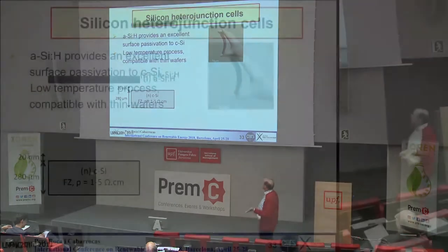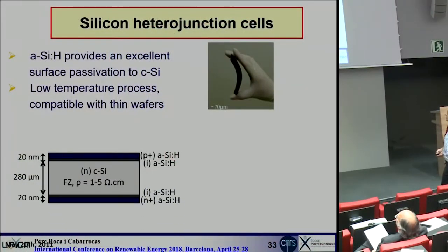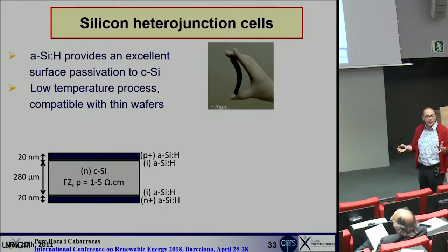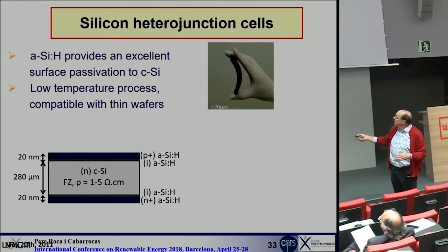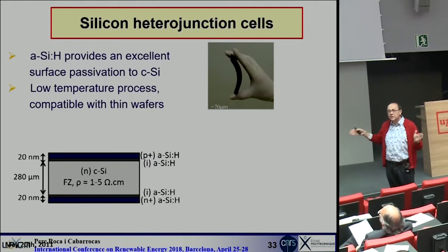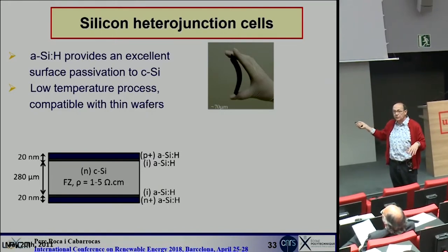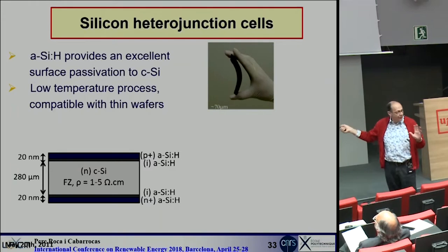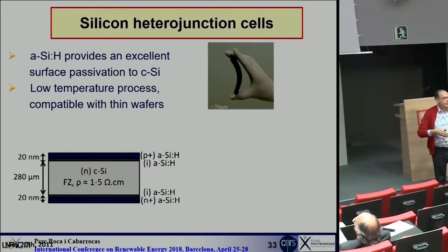Heterojunction solar cells: we are going to change the substrate, instead of having glass or foil, we are going to work on crystalline silicon. That's the battle horse. So let's take crystalline silicon, and then the same, you put it in the reactor, you deposit the intrinsic, p-type, intrinsic, n-type, so this is fast. Those layers are really thin, 20 nanometers, and they allow to get, today, record efficiency. Crystalline cells are based on this. So they already combine crystalline silicon and thin film.